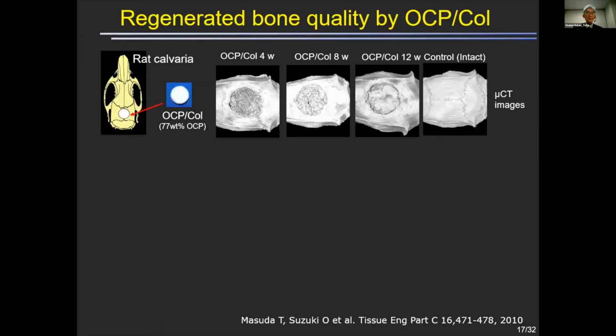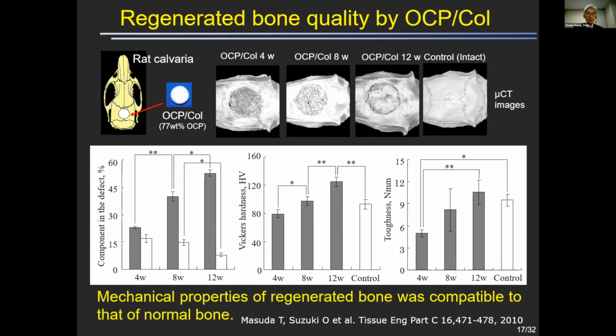And we investigated regenerated bone quality by OCP collagen implantation. And you see the gradual increase of radiopacity over the time. And this is a rat critical size defect model. And this figure indicates the bone formation gradually, you see the gradual increase and also gradual decrease of the remnant of OCP. So this is the biodegradable property as I mentioned before.